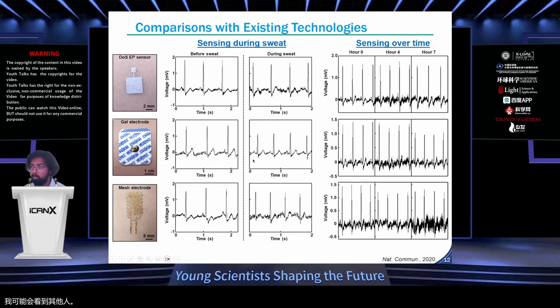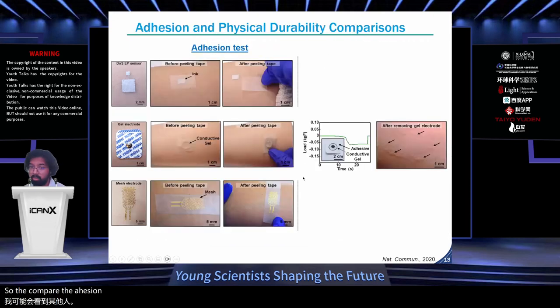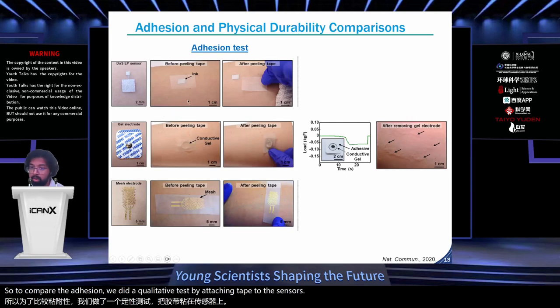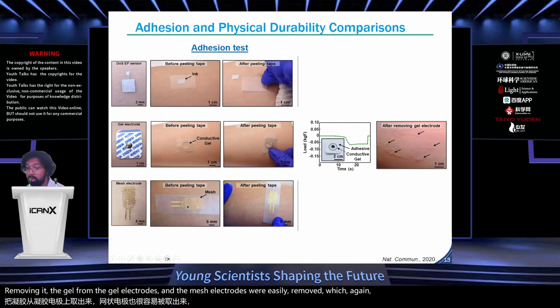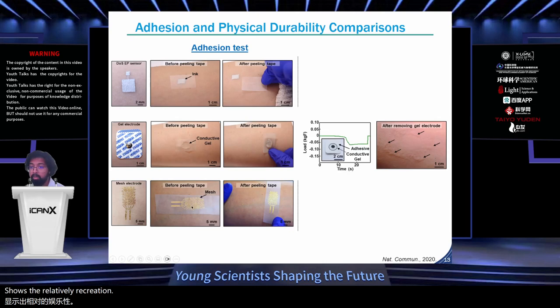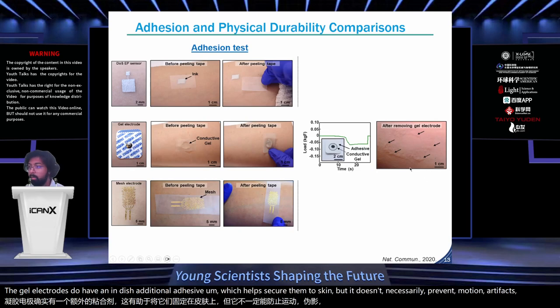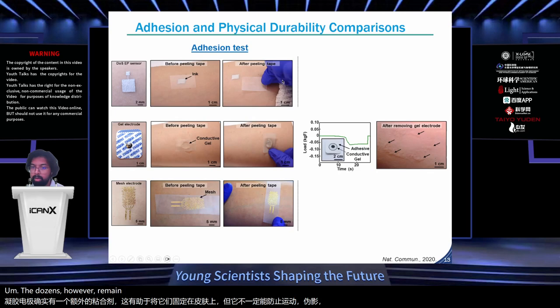To compare the adhesion, we did a qualitative test by attaching tape to the sensors and removing it. The gel from the gel electrodes and the mesh electrodes were easily removed, showing relatively poor adhesion. The gel electrodes do have an additional adhesive, which helps secure them to the skin, but it doesn't necessarily prevent motion artifacts. The DOS sensors, however, remain pretty much intact after this.